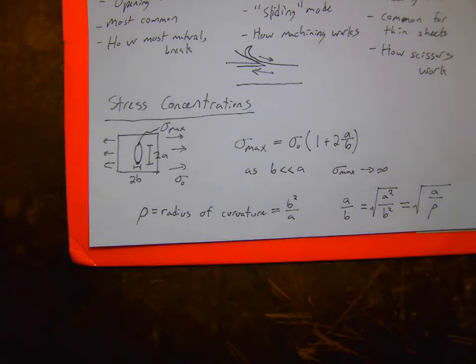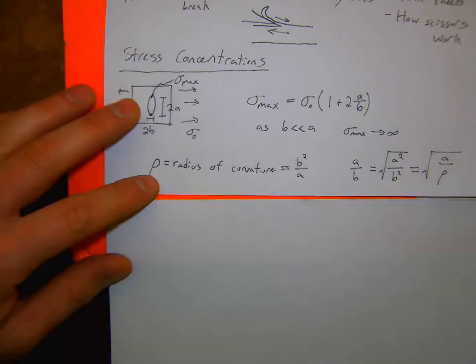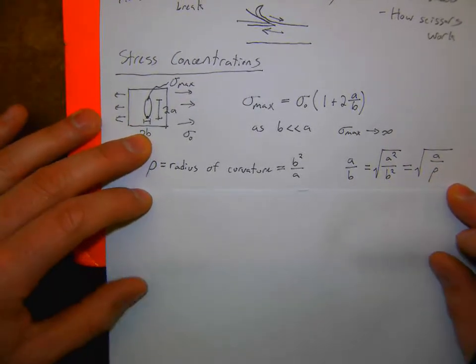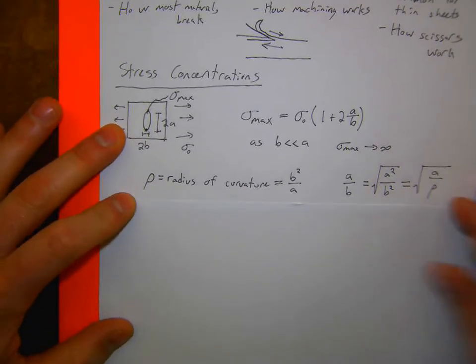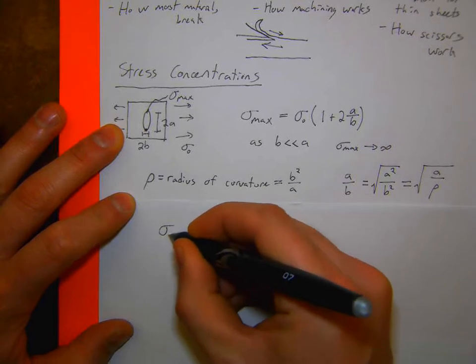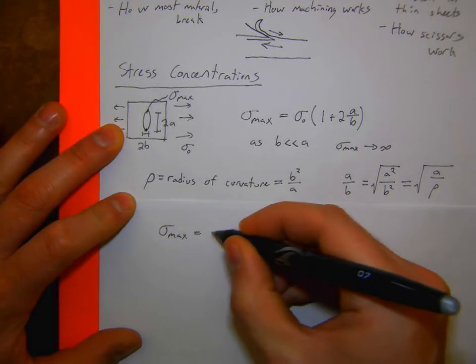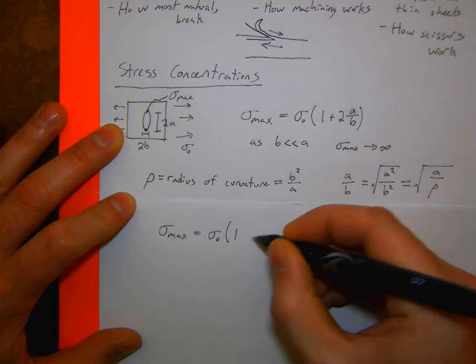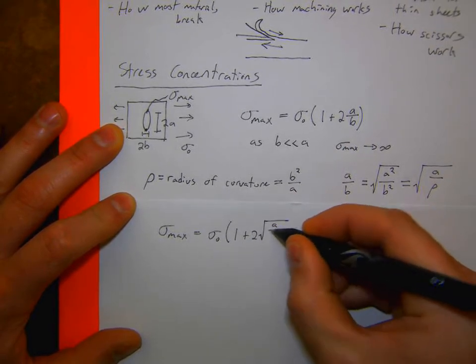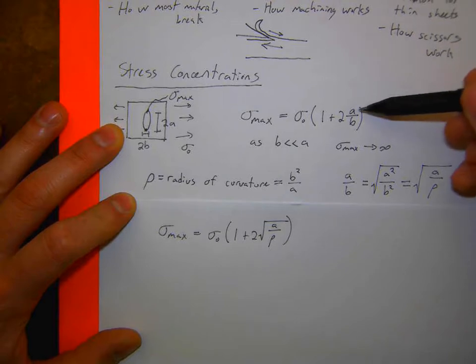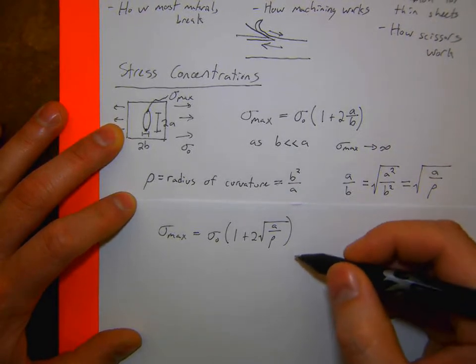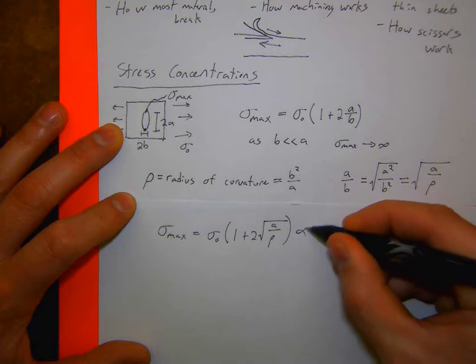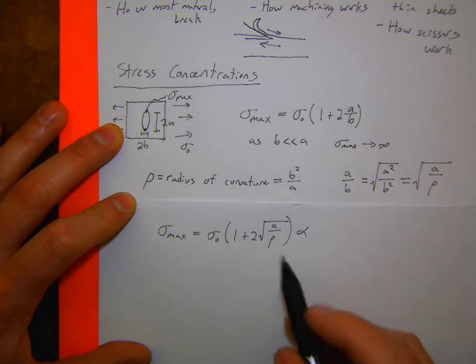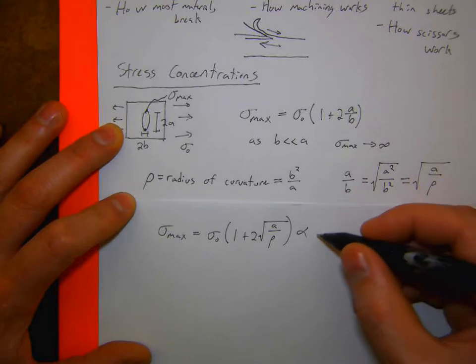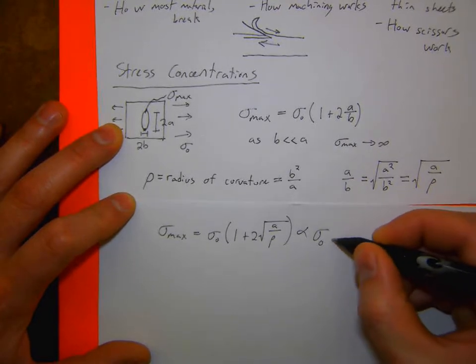So now I can rewrite this whole equation for sigma max in terms of my radius of curvature. The maximum stress is sigma naught times 1 plus 2 square root of a over rho, a direct substitution based on that radius of curvature. Now as rho becomes very small, this is proportional to sigma naught square root of a.